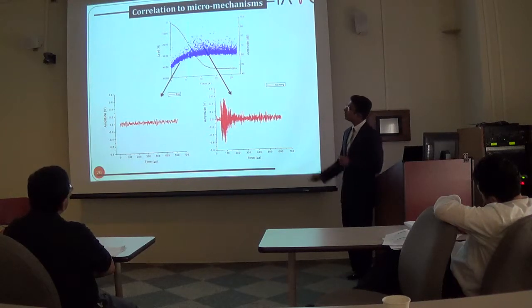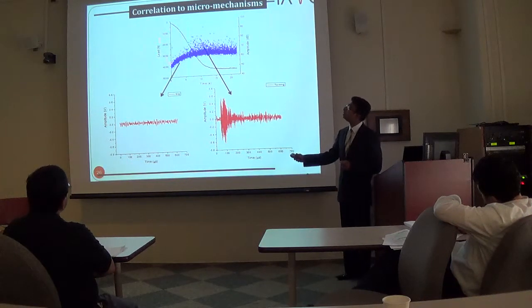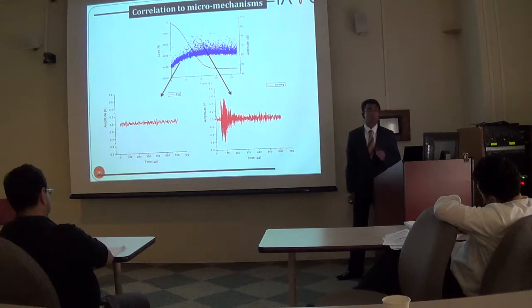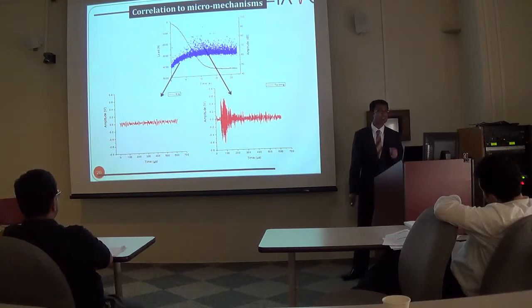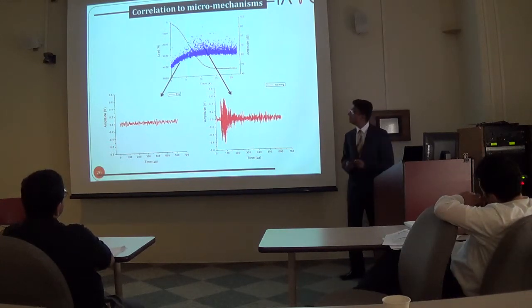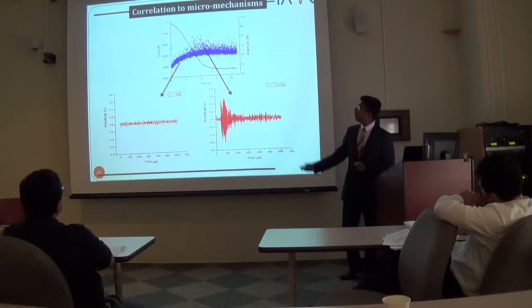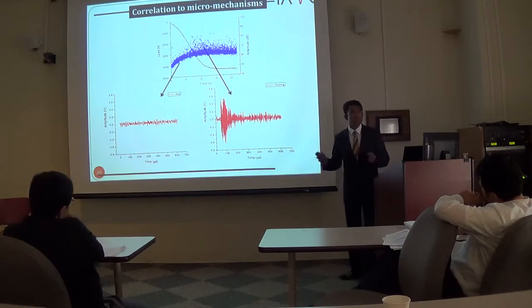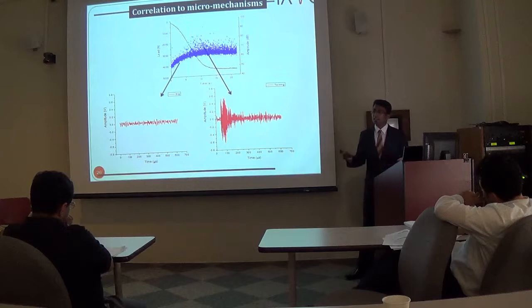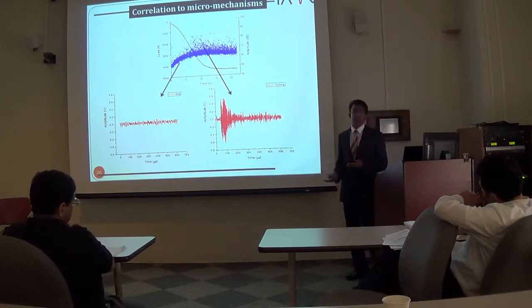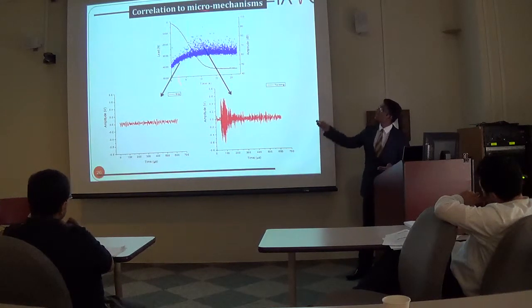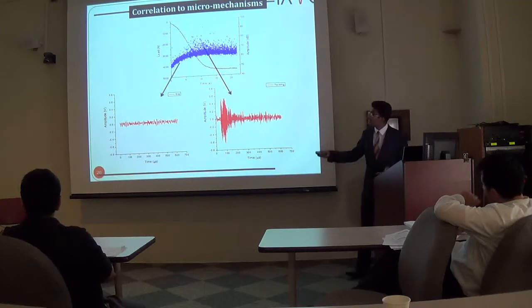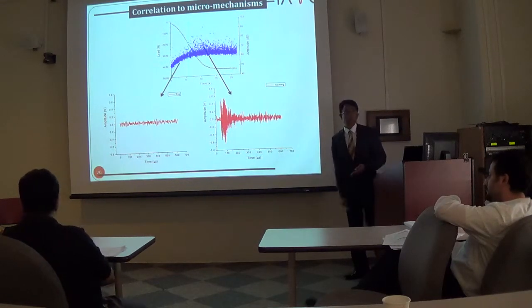What was interesting to note was that the AE waveforms that were picked up before the 6 seconds were very low amplitude and are characterized by continuous type emissions, while the AE waveforms that were picked up after the 6 seconds were much higher in amplitude and also had a burst type emission. Thus, you can clearly see how the wave signatures evolve after a specific time in the load, and in the instant where you can see a shift in the wave signatures.